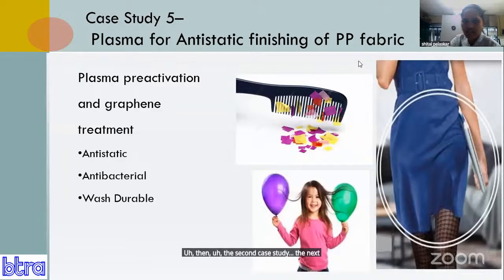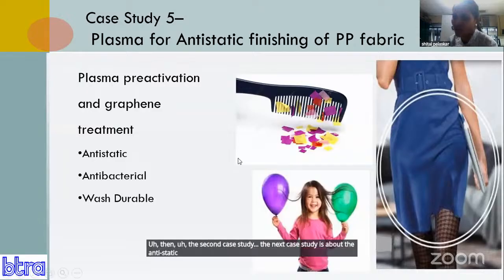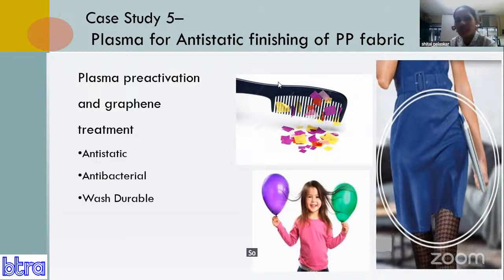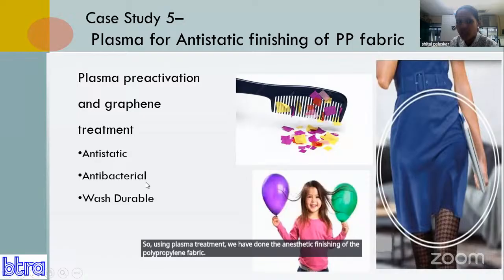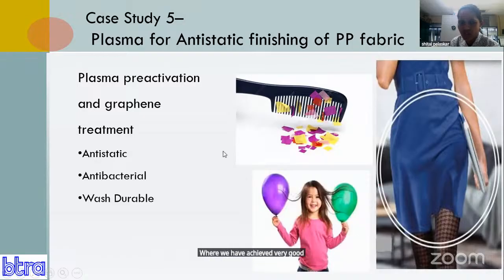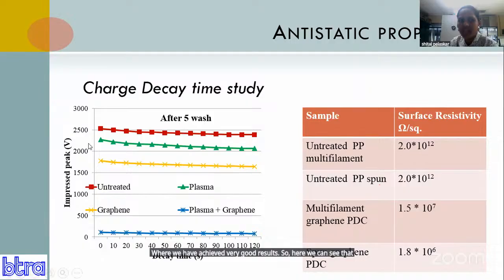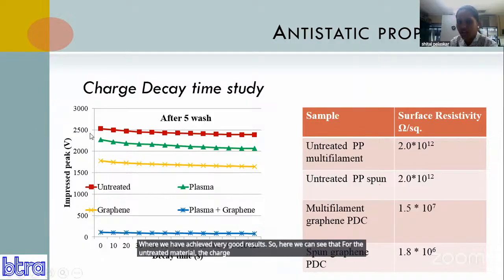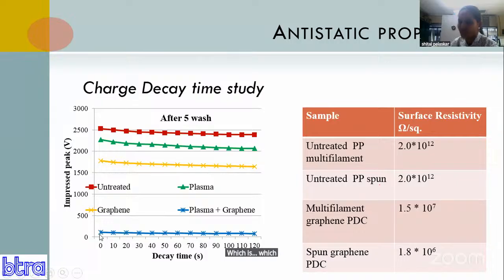The next case study is about the anti-static finishing of polypropylene fabric. As we all know, static charges are very dangerous in day-to-day applications. So we need to have anti-static finishing. Using plasma treatment, we have done the anti-static finishing of polypropylene fabric, where we have achieved very good results. For the untreated material, the charge generated on the surface is very high, whereas after treatment, the charge generated is very low, which reduces the risk of static charge.